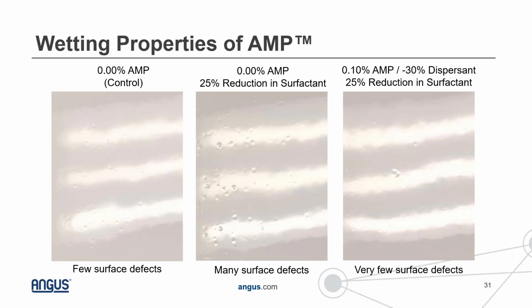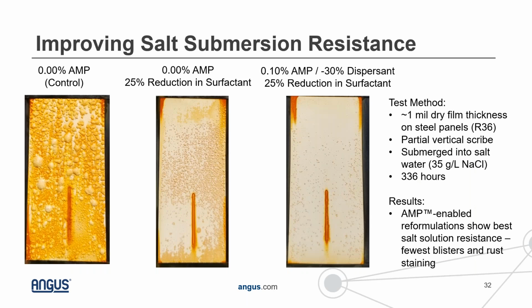But what we noticed is that if we reduced our surfactant concentration by about 25%, you really start to see a lot of defects, right? That surfactant was really necessary to eliminate a lot of the craters and the pinholes that we see when we reduce it. But if we take that same formulation with the reduced level of surfactant and we reformulate it with the 0.1% AMP along with a 30% reduction in dispersant, we see very few surface defects. So AMP can really help you formulate to reduce the level of surfactants in this particular formulation, and you can still get a very good quality film surface.